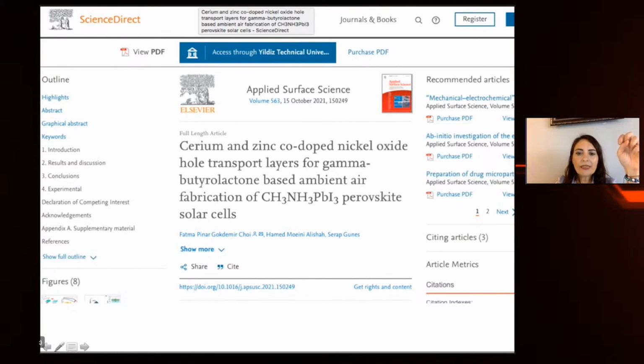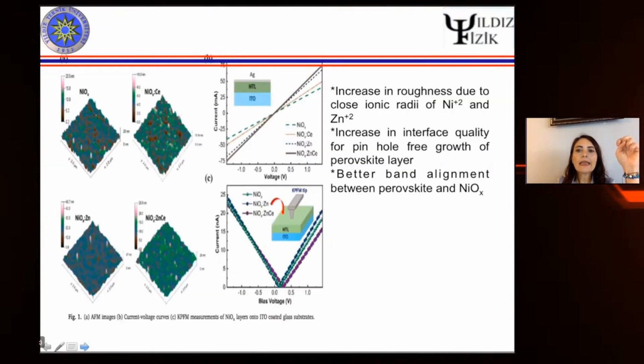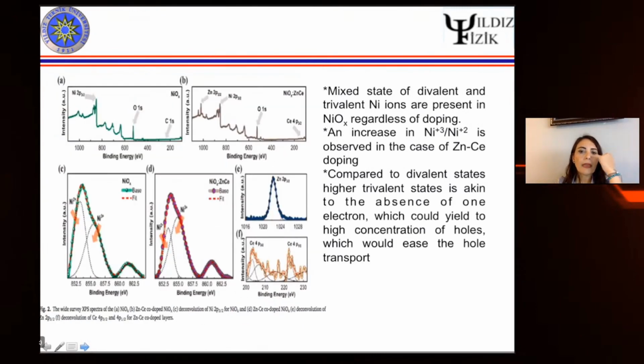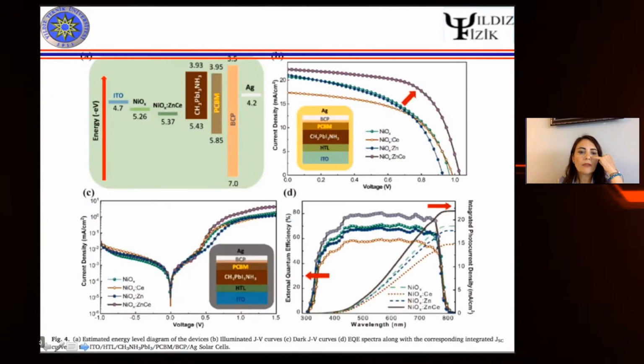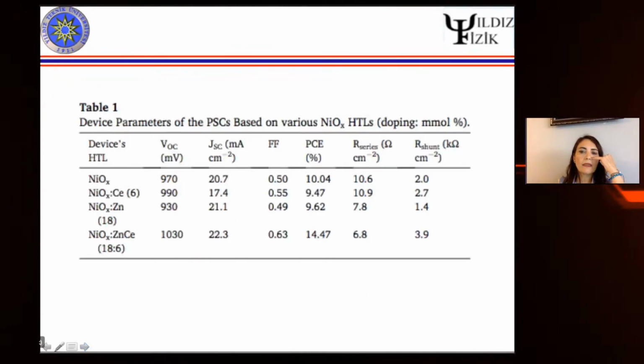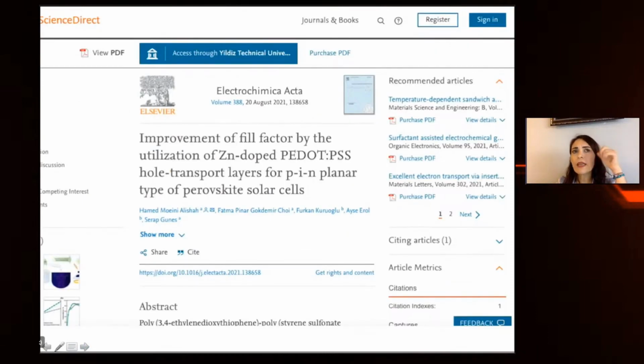Therefore, we put this ambient air fabrication of this methylammonium lead iodide based perovskite solar cells. And as a result of the doping, we have realized that we have a better band alignment between the perovskite and nickel oxide, and also we have increased the interface quality for pinhole-free growth of the perovskite layer. And these are the results also from the same publication. We see these are the efficiencies. The efficiencies were improved from 10 to almost 15%. Of course, this is lab scale, 1.5 by 1.5 centimeter scale.